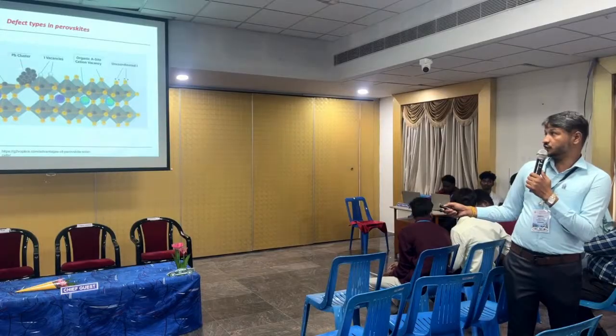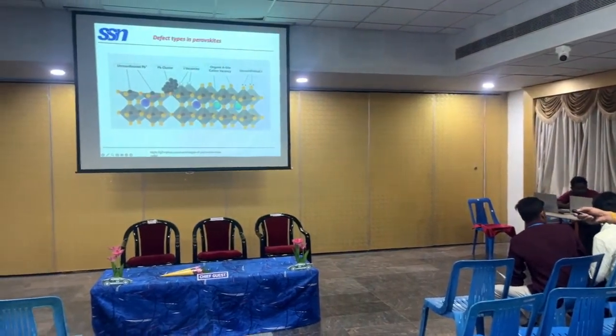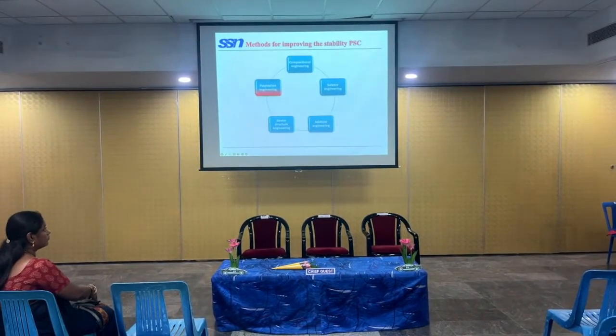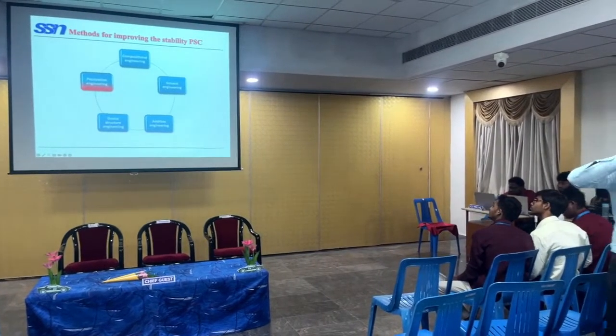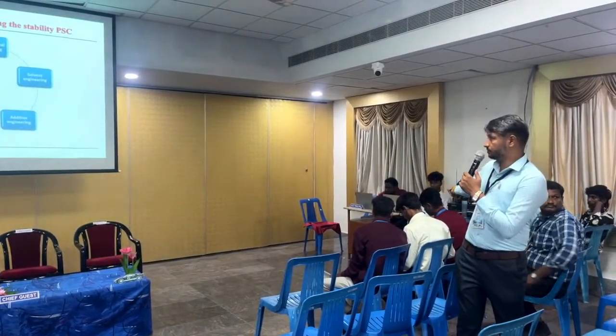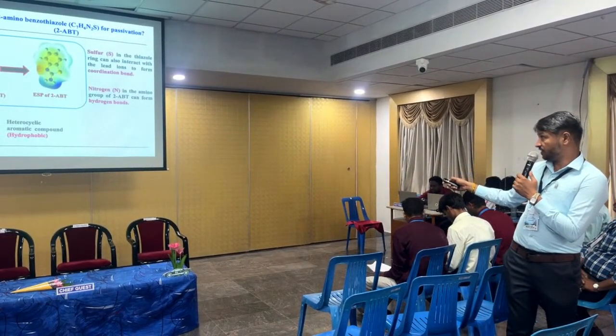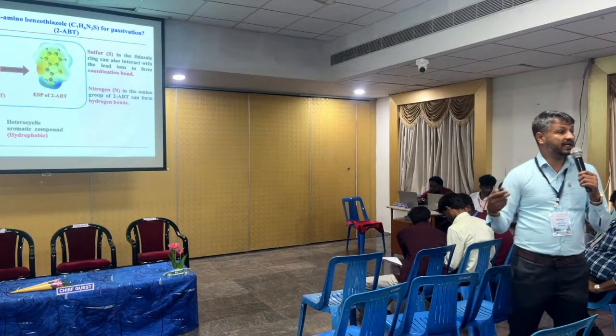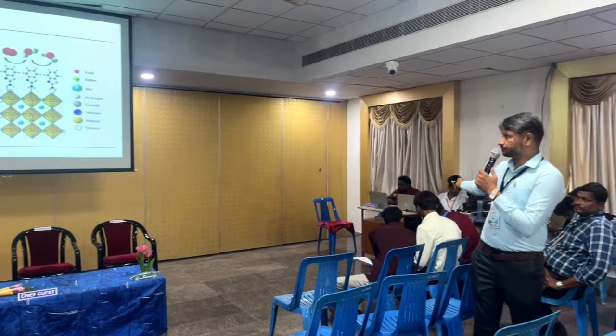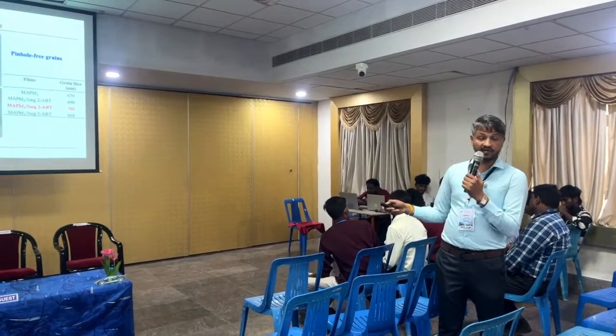The structure itself has a lot of issues, uncoordinated lead ions, Pb lead clusters and so on. So in order to avoid such things, my student did a passivation engineering approach to passivate the defects in the system. He took one organic molecule, 2-ABT, a 2-aminobenzothiazole unit. It has sulfur and nitrogen atoms. It coordinates with uncoordinated lead ions in the perovskite system. You see, with conventional methylammonium lead iodide perovskite, you have pinholes. After introducing the 2-ABT, you see there are no pinholes. He used 3 different concentrations. You see the pinholes we avoided, which act as recombination centers.